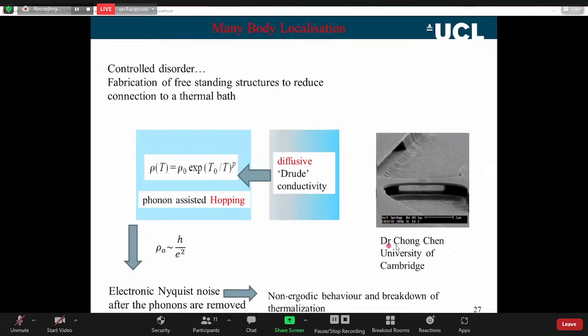So this is an SEM image from my co-workers in Cambridge. She's produced this structure. This is actually a selectively etched freestanding Hall bar. So this is part of the Hall bar that I showed you before. It's actually in indium gallium arsenide, not in germanium or germanium-tin. But we could use the same processing. You can see actually the very faint light line there, and that is an indium gallium arsenide quantum well. So we can make freestanding quantum wells. And the interesting part of this device is that it's not connected, or it's very, very weakly connected to the thermal bath. But it's not connected to the substrate. There's an air gap here, and it's only weakly connected to the contact.